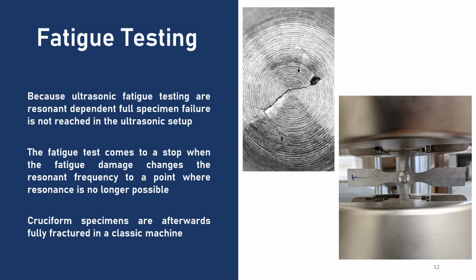Now, because ultrasonic fatigue testing machines are resonance dependent, we cannot achieve a fully fractured specimen. As the fatigue fracture grows, the specimen loses rigidity and therefore it loses frequency, making the setup lose the resonance frequency at the working frequency of the transducer, and therefore the ultrasonic fatigue machine comes to a stop. To have access to the fatigue fracture, the specimen must be put under a classical machine to make the final fracture of the specimen. In this case, we put the cruciform specimens under tensile forces in the classical machine and obtain a fully fractured specimen.